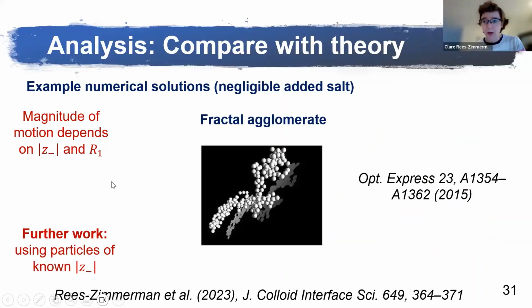It's just that having a quantitative comparison here is difficult because the silica nanoparticles aren't actually spherical. They form fractal agglomerates, like shown in this image. I therefore carried out more experiments using particles that were manufactured by Steve Armes' group in Sheffield Chemistry. They made us spherical particles with a known number of surface charges. I repeated the same experiments and got very similar results. Perhaps our theory still slightly overpredicts the motion that we see experimentally. That's likely because my equations are valid for dilute solution and they don't account for hydrodynamic hindrance. This work is published here if you're interested.